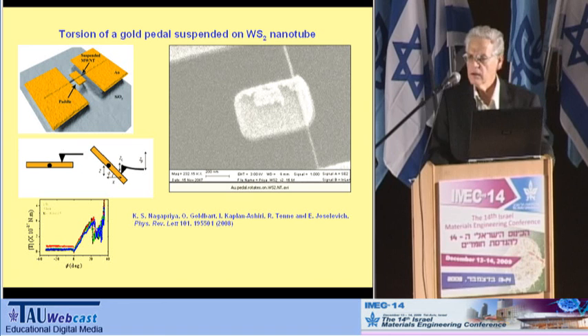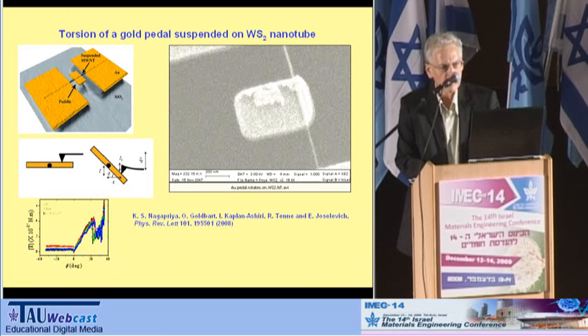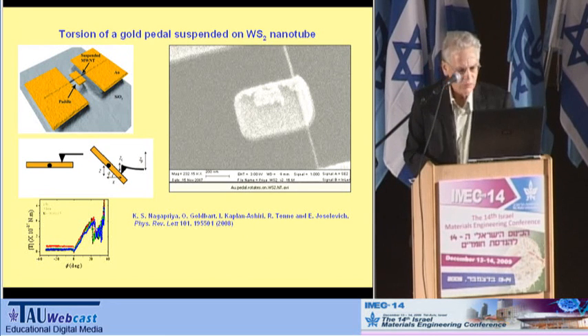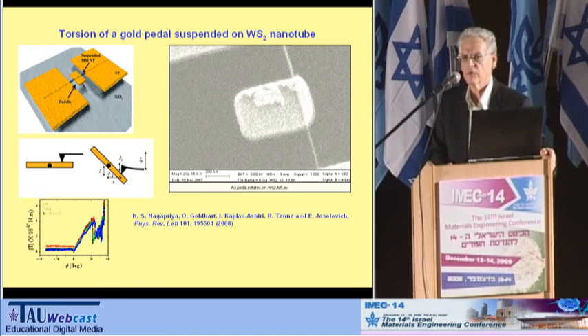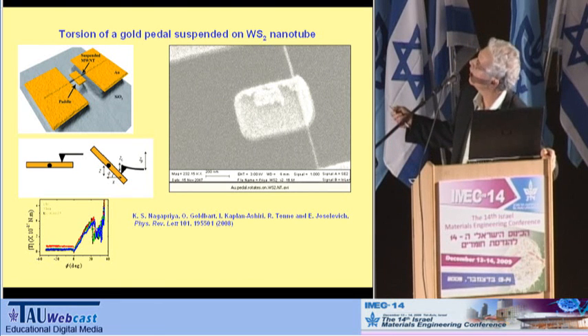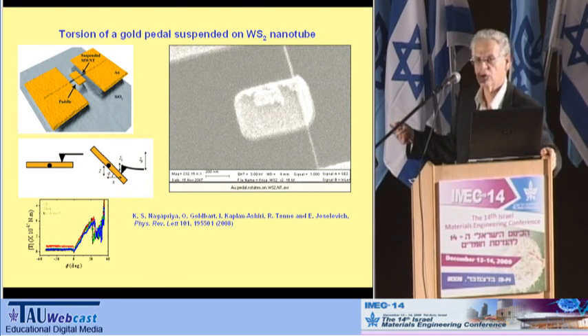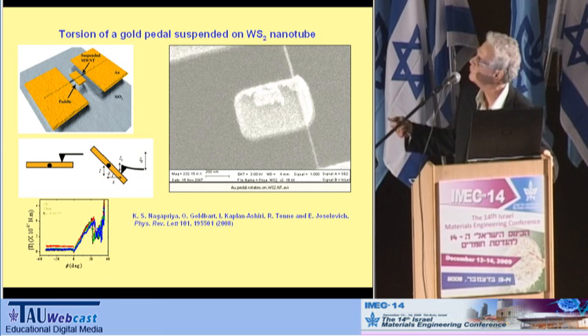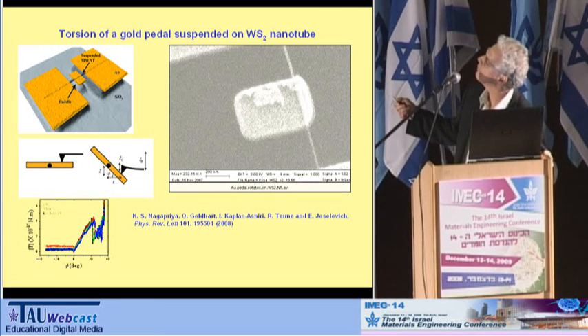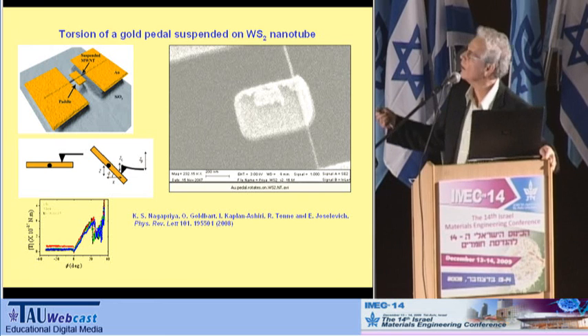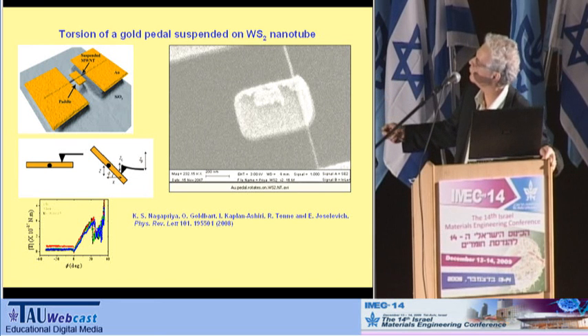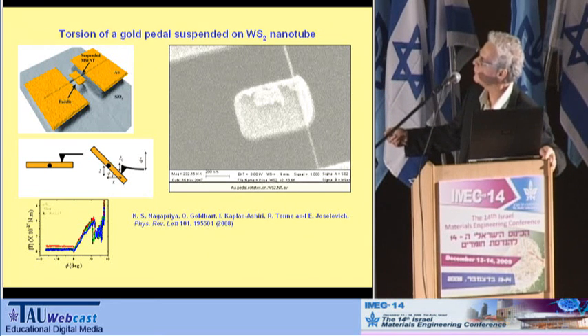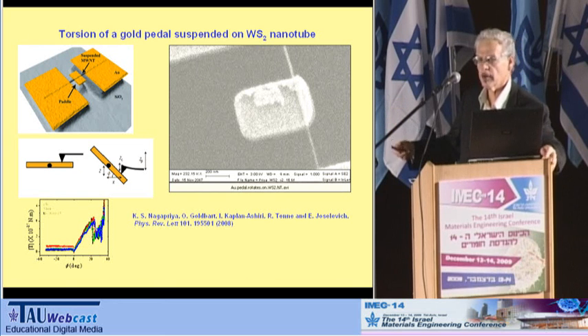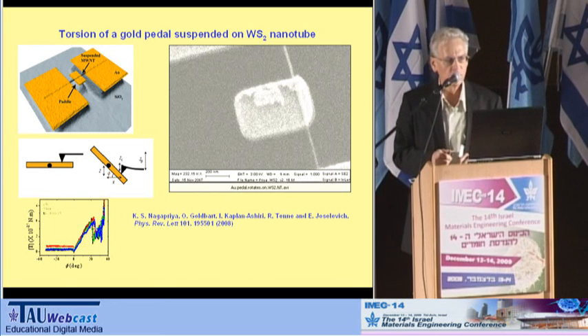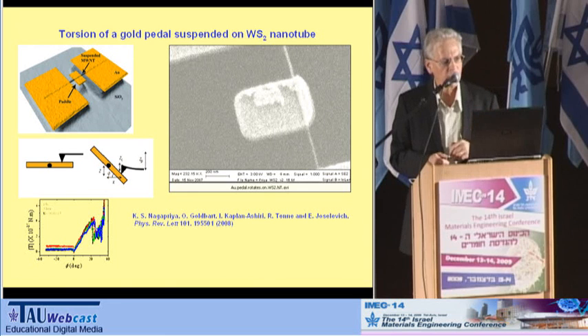In another study that we undertook together with Professor Ernesto Joselevich, we have studied the mechanical behavior of the nanotubes. Basically, what you do, you use a nanolithographic method, and you apply a gold pedal on the nanotube, and you can then use an AFM to press on the pedal and see the progression of the torsion of the nanotube. And indeed, you see that they really do not fail.